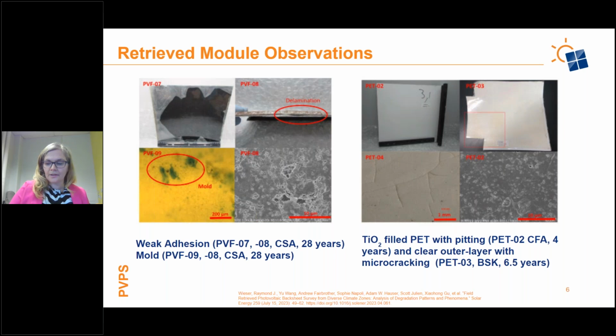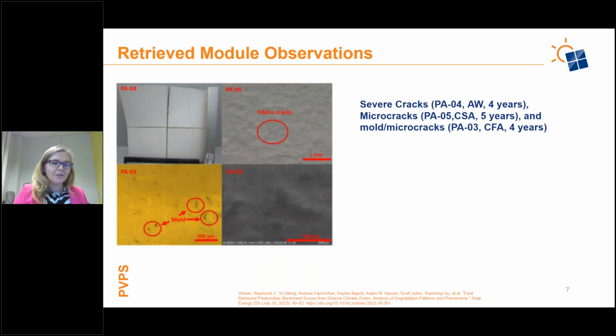Some observations here: for PVF, we saw some delamination. These were also modules that had been exposed in California for 28 years. We also saw mold growth on those. For PET, interestingly enough, we saw pitting in modules that were 4 years old. We also saw some modules with a clear outer layer PET, so they were not filled with TiO2, and in those cases we saw microcracking. And additionally, just like I had said, we saw these polyamide backsheets with severe cracking in between the cells, and also microcracking and mold growth.